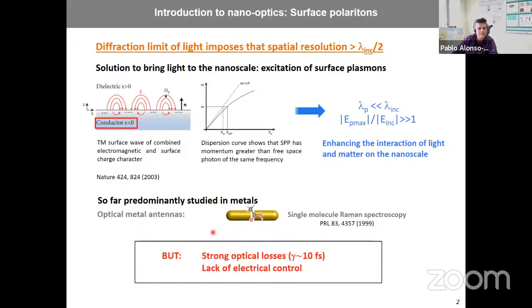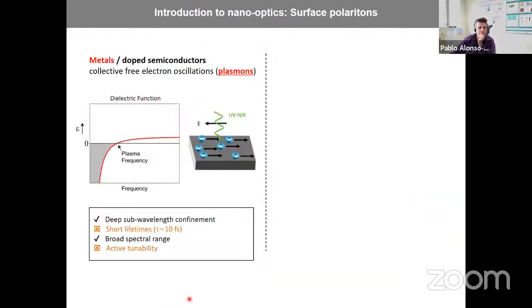This Raman signal. But let me say that plasmons also show some drawbacks. For example, they have strong optical losses. The lifetime of these surface plasmon polaritons is in the range of 10 femtoseconds. This is because electron-electron scattering is the physical mechanism that dominates and makes the wave decay very fast. And there is also a lack of electrical control. Because if you just put an electric field, it is screened out by the metal itself, and then you cannot control the properties of polaritons in an active way. So, okay, this is a summary of surface plasmon polaritons in metals.